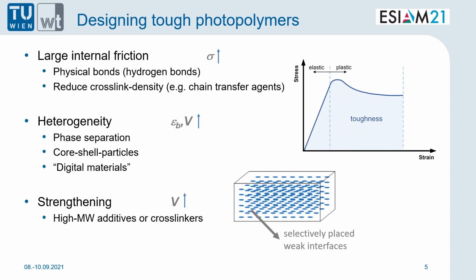So when designing potentially tough photopolymers, there are several paths which you can follow. Either one can increase the internal friction by introducing hydrogen bonds or any other kind of physical bonds, or reduce the crosslink density by, for example, using chain transfer agents. Or you can strengthen the material by using high molecular weight additives or using crosslinkers. And when using core-shell particles or having phase separations or weak interfaces, you introduce heterogeneity into your system, which then again can increase the plastic zone and therefore reduce the crack propagation.